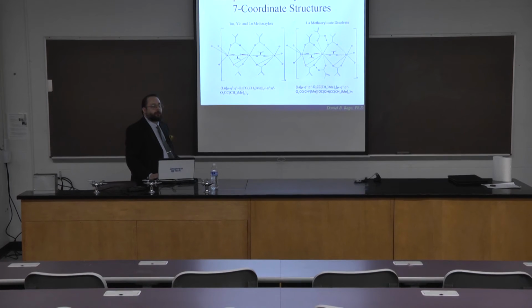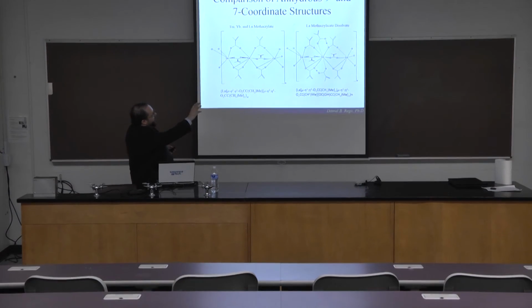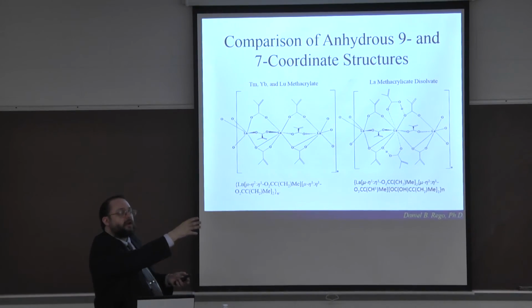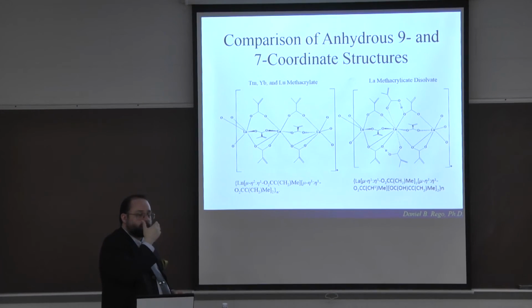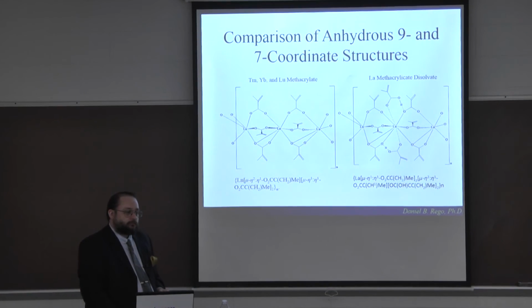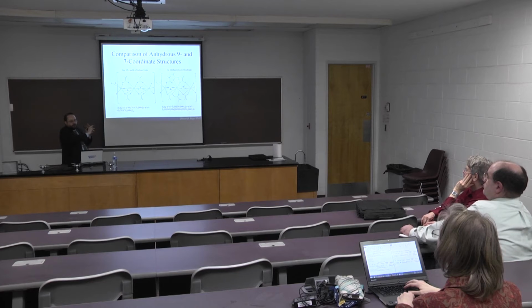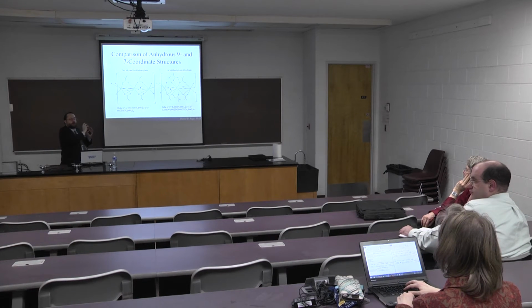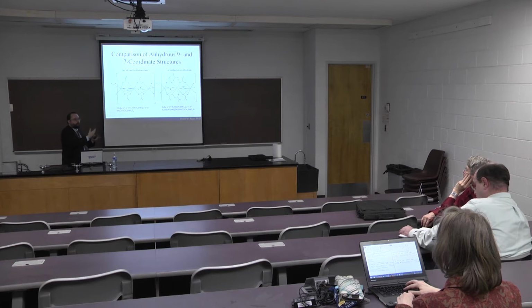Well, there might be a possibility where you just have a single infinite chain of pure 8-coordinate and a pure chain of pure 7-coordinate. But I could talk to our computational chemist, and a random disorder would, according to them at least, make most sense. It's really right there between a pure 8-coordinate and a pure 7-coordinate. You can see how it slips between the two. Right, that happens all the time. But regardless of whether it's all in the same chain, or different chains, we're still seeing both coordination modes in the same overall structure.